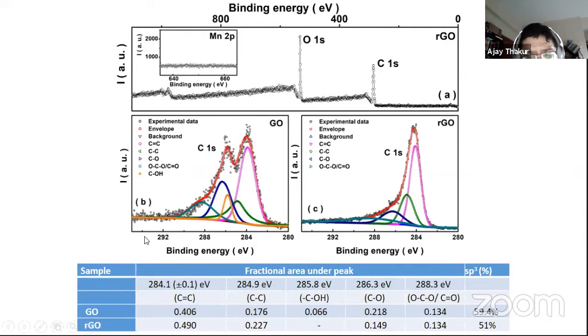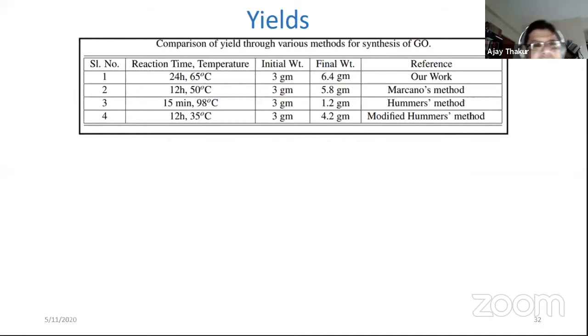And while doing so, it is very important to make sure that the binding energy values that you use for doing this multi-peak fit are as identical as possible between the graphene oxide and the reduced graphene oxide. Because if you don't do it, then just because of its inherent nature of being a multi-peak, multi-parameter fit, anything could be fitted to anything else without giving meaningful results. So that is a crucial step which people have to be careful about.